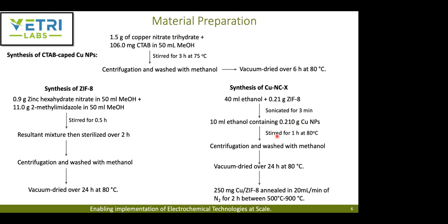They took 250 milligrams of the copper ZIF-8 and annealed it under about 20 ml per minute of nitrogen for a total time of 2 hours at different temperatures, and they named the samples with X, which we'll see, along with their activity, in the later slides.